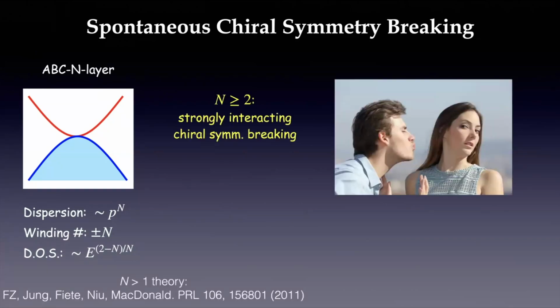Okay, so it turns out, because of this interaction, there is a very strong interacting chiral symmetry breaking. So the result is that these two bands don't like each other. They don't want to kiss each other. There will be a gap opening right here. Okay, so this is also the first time we show the Dirac mass projection in this beautiful system. And if we only look at single valley, single spin, the electrons will tend to polarize in one of the 2 layers. Okay, so they are polarized per flavor.